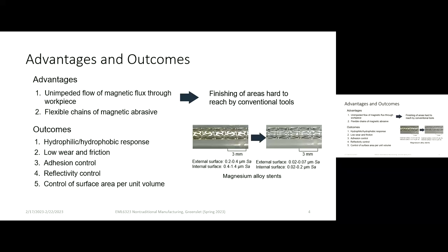All right, here's a picture before and after polishing using MAF, on the left side versus the right side. On the right side, you should hopefully see that it's much shinier. We have some Ra values to quantitatively show you the impact that MAF has had on the surface. On the external surface of your stent, the original surface was 0.2 to 0.4 microns, or 200 to 400 nanometers Ra, and they were able to polish it down to about 10% of what it was before. So now it's 20 to 70 nanometers.